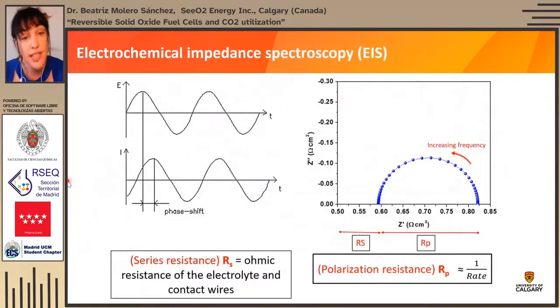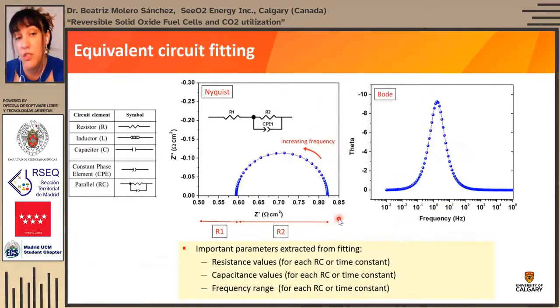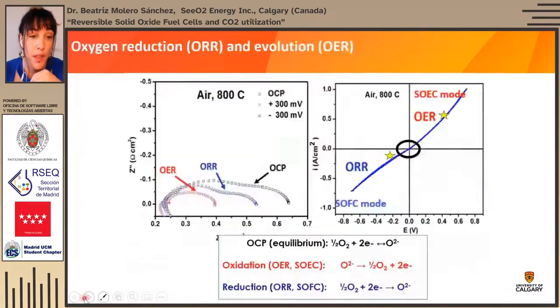One of the main techniques used to characterize this electrocatalyst is electrochemical impedance spectroscopy. Here one of the main parameters that we look at is the RS, or the ohmic resistance, which is the series resistance, the contribution from the ohmic resistance of the electrolyte and the contact wires, but also the polarization resistance, or RP, which is inversely proportional to the reaction rate. By fitting all of these results with equivalent circuits, we can extract many parameters such as resistance, capacitance, and frequency ranges, and these values are really important to help us understand the physical processes in these materials and then the reaction mechanism levels.